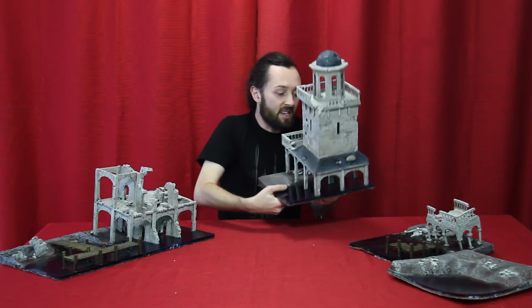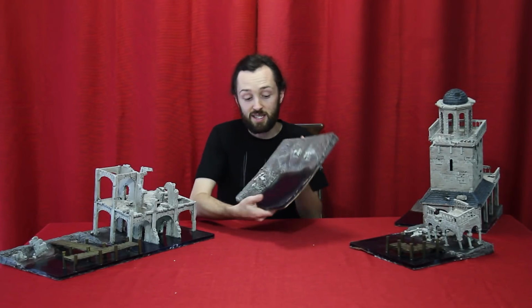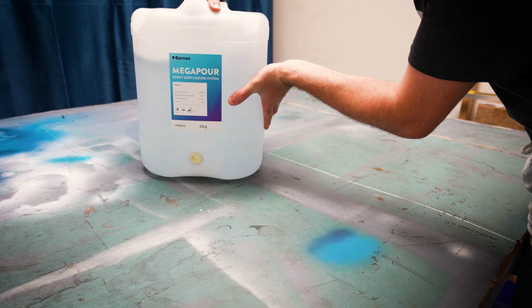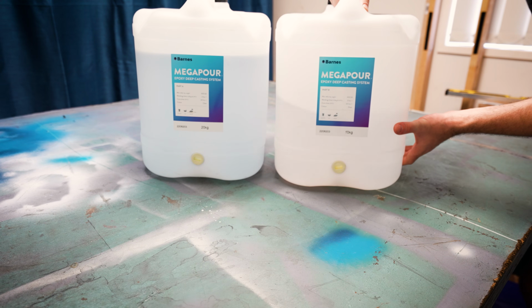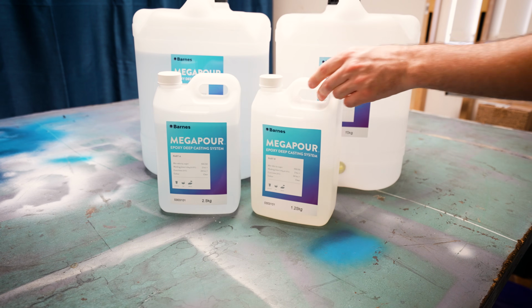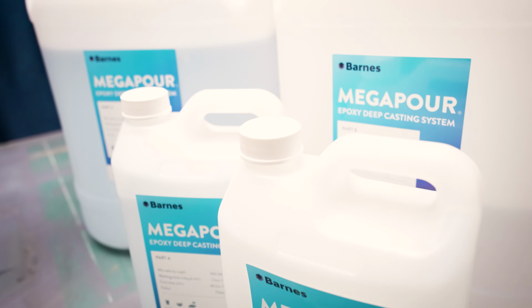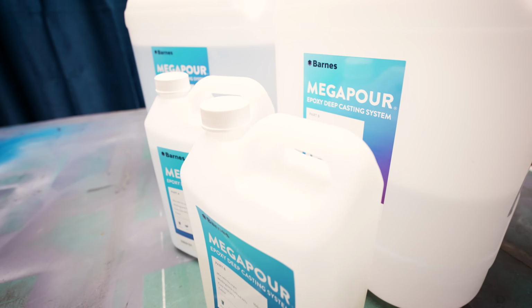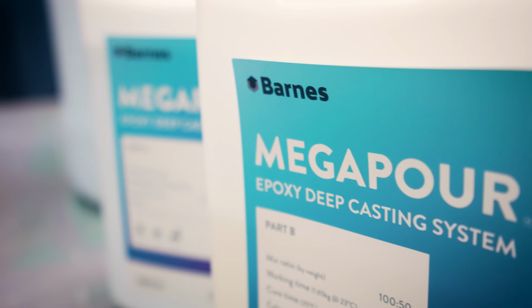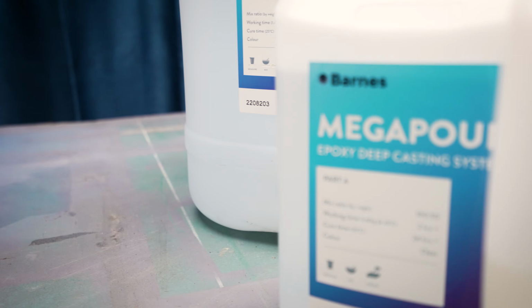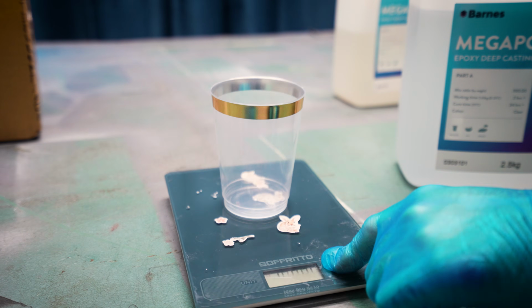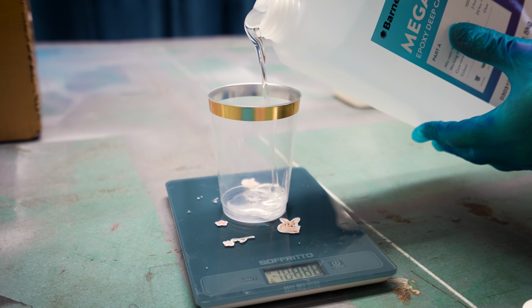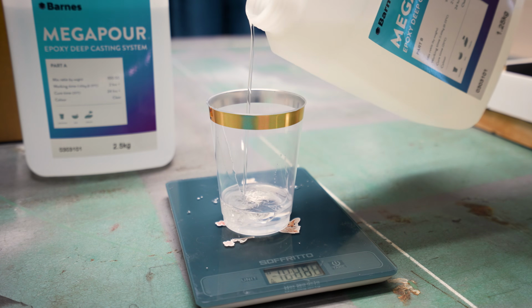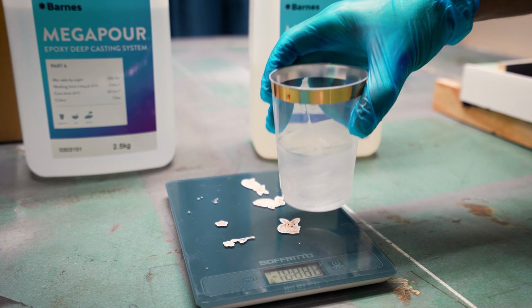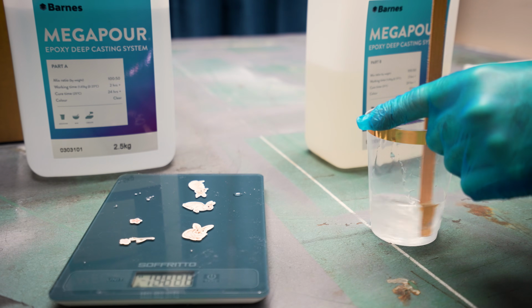And recently, the folks over at Barnes have developed a new type of epoxy resin called Megapour. This beast has a working life of 2 hours and a cure time of 24 hours, so there's heaps of time for bubbles to escape, and it's not going to set on me too quickly. Ages ago, I bought a 3.5 kilo kit to attempt the first build, and then Barnes, when they heard about the project, sent over a full 30 kilo kit, so we are armed to the teeth with epoxy resin. So a big thanks to the team over at Barnes.